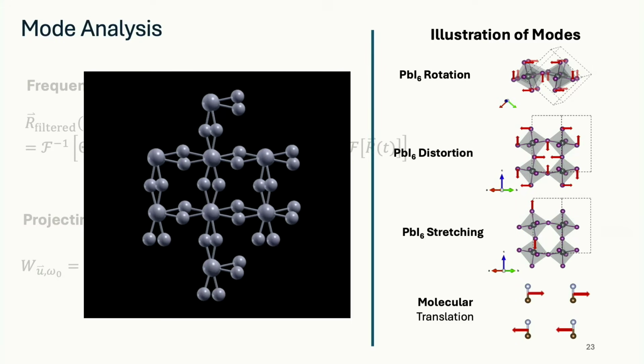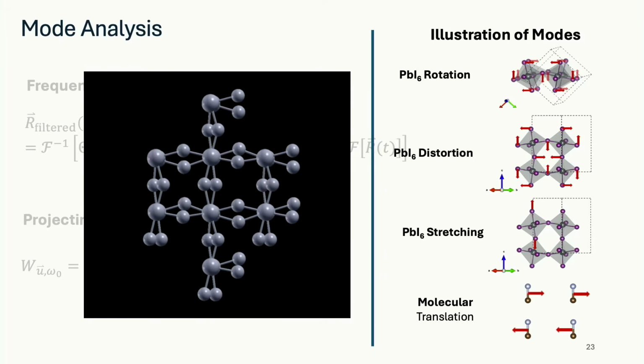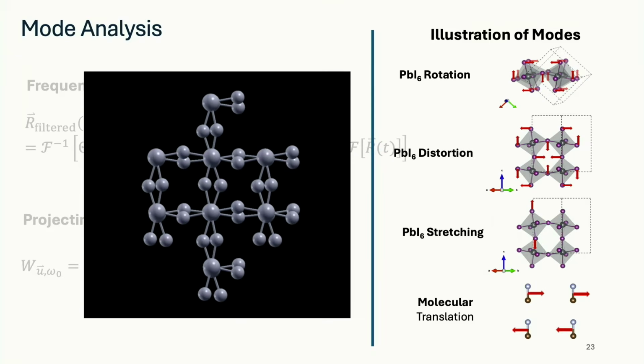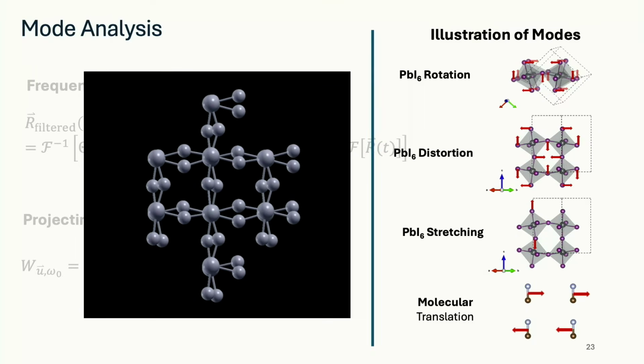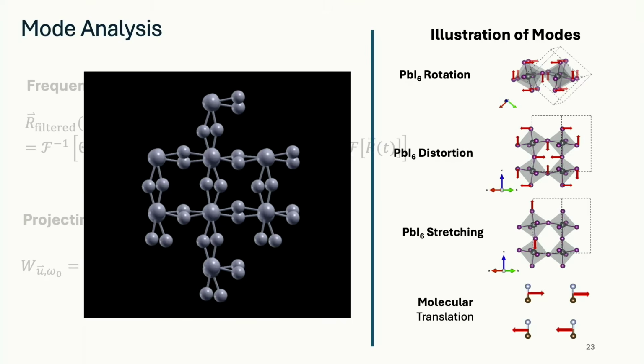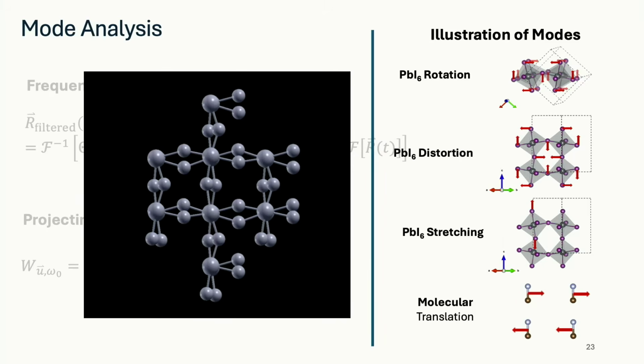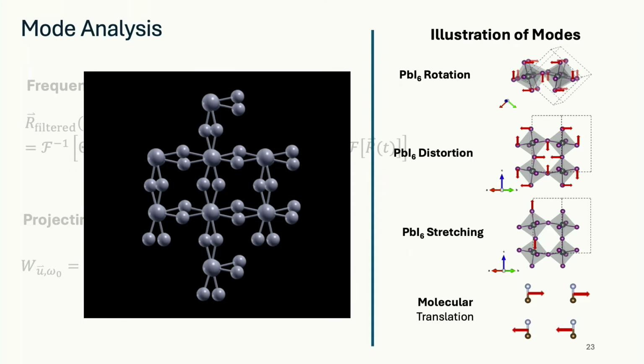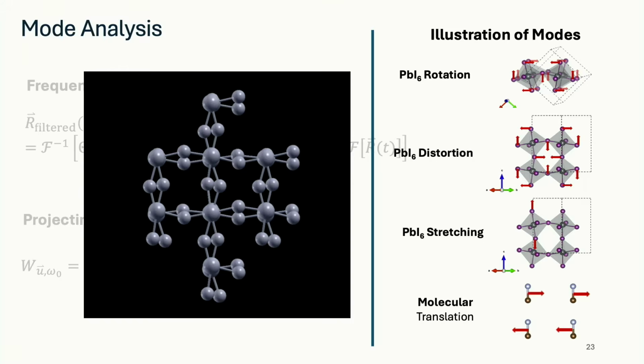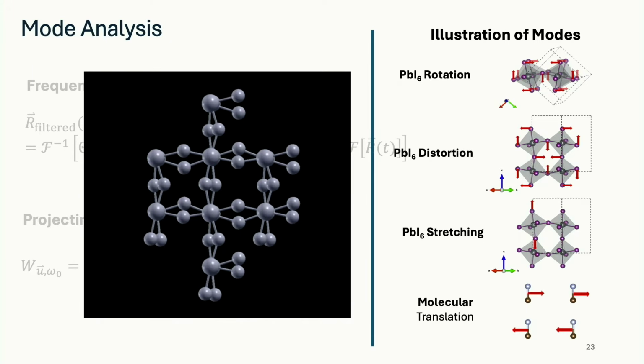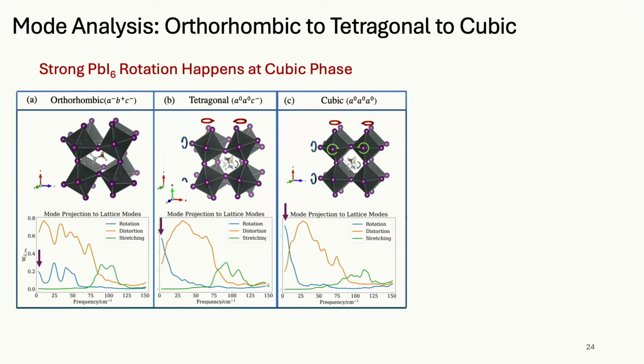So you can see one particular behavior, but it's not really a phonon mode, because we could look at any frequency in that featureless blob and we can ask, what is it doing? And so it turns out it's doing a complex combination of things. It's doing PbI6 rotations, PbI6 distortions, and PbI6 stretches. It's all the octahedra at these low frequencies. So then we can decompose and diagnose. And at the lowest temperatures, it's a lot of distortion, it's a little bit of stretching, and it's a little bit of rotation.